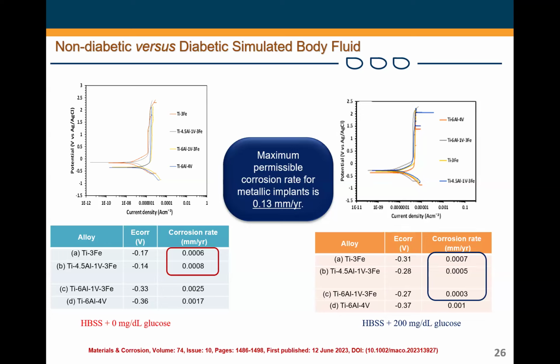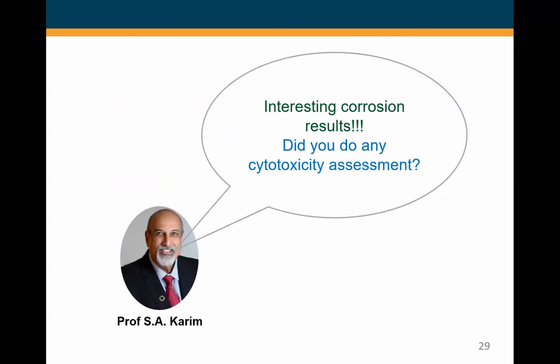Again, our conclusion would be that partial substitution of vanadium with iron is beneficial for corrosion resistance. And we need more work to be done in that area so that we can settle the argument that iron has a negative influence when you add it to titanium. It does not only reduce cost, it can give you improvement in mechanical properties and corrosion performance. We managed to convince experts within the scientific space by publishing some of our findings in all of these journals.